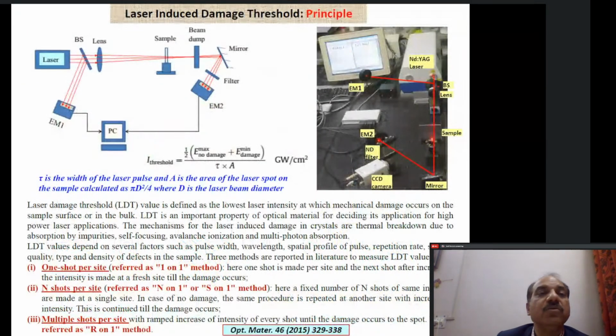And we regularly use a laser-induced damage threshold setup for investigating the damage threshold value of our grown crystals. The laser damage threshold value is defined as the lowest laser intensity at which mechanical damage occurs on the sample surface or in the bulk. LDT is an important property of an optical material for deciding its application in high power lasers. The mechanisms for laser induced damage in crystals are thermal breakdown, absorption by impurities, self-focusing, avalanche ionization, and multiphoton absorption. There are various ways in which LDT values can be measured, referred to as one shot per site, n shots per site, or multiple shots per site.